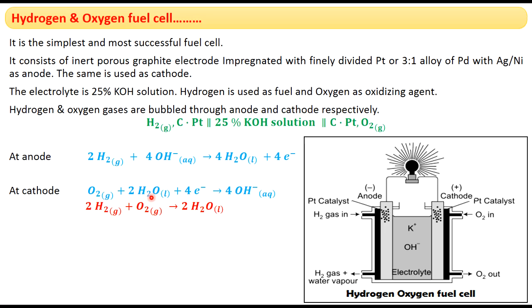At the cathode, the reduction reaction is: O₂ + 2H₂O + 4e⁻ → 4OH⁻. Four water molecules produced at the anode — two of which are consumed at the cathode — and four electrons arriving from the anode are consumed. Four OH⁻ ions are consumed from the electrolyte at the anode, and four OH⁻ ions are regenerated at the cathode, so there is no net consumption of electrolyte. The overall reaction is: 2H₂ + O₂ → 2H₂O.